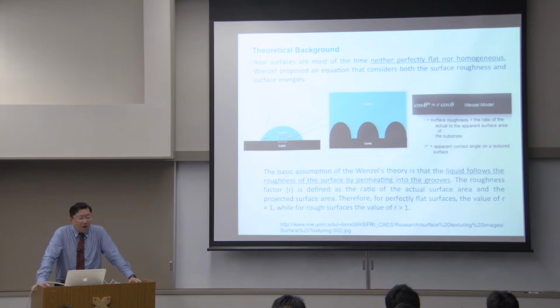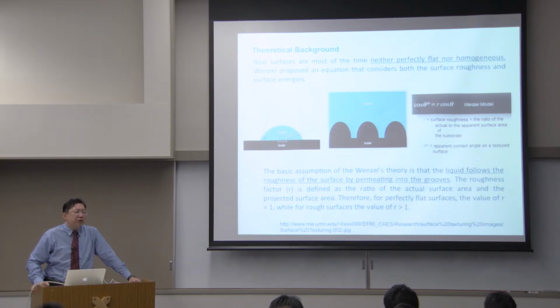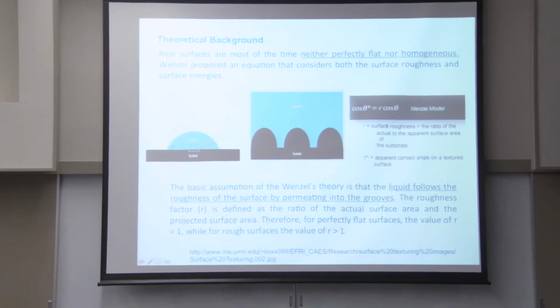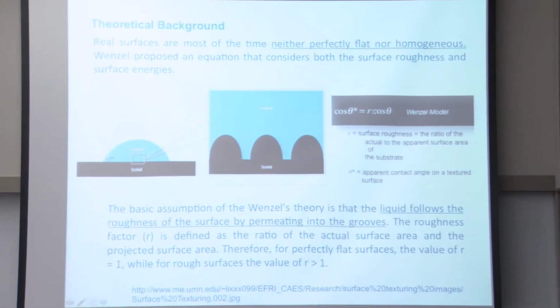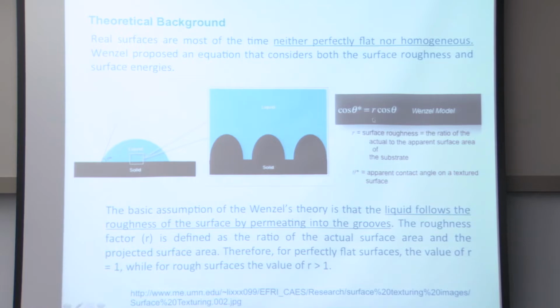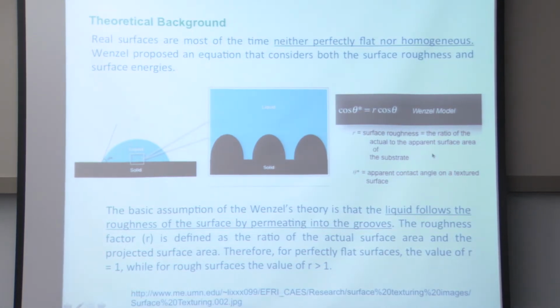Now the second type of interaction is basically accommodating the effect of roughness. If you have a surface that is not homogeneous in surface energy or not flat, when you introduce this roughness factor, the correction can appear on this side of the equation, as R times cosine theta, giving you what we call the Wenzel model.